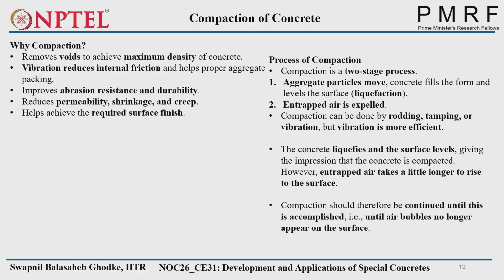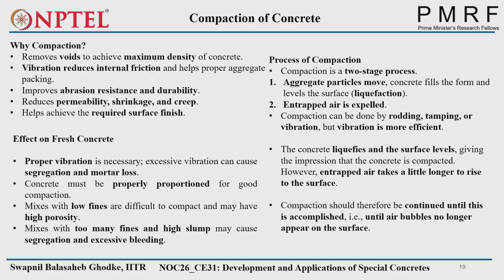When you are compacting concrete using a vibrating table also, initially some workability will improve and you will see the compaction will be fine. But if you continue a little bit more time, a certain amount of voids or bubbles will be seen on the surface, coming out of the concrete matrix. So you have to take care of that. So how does it affect the fresh concrete? Proper vibration is necessary.